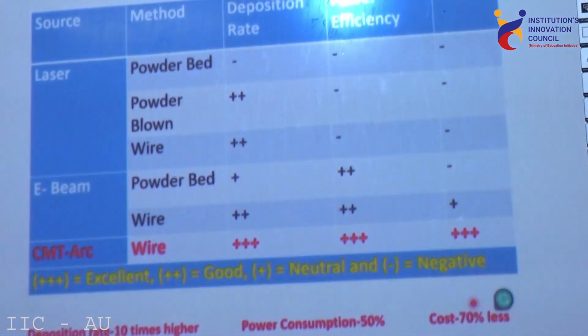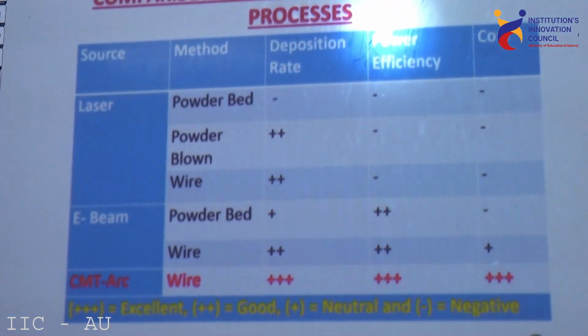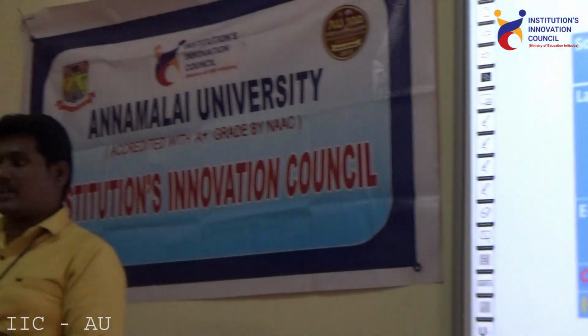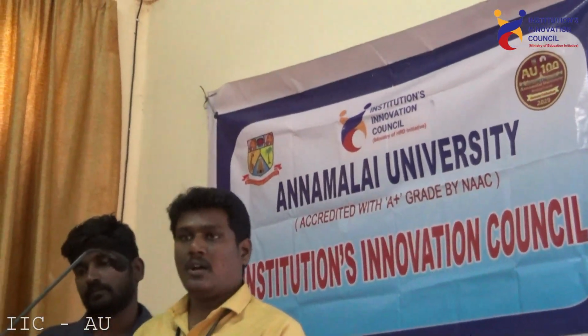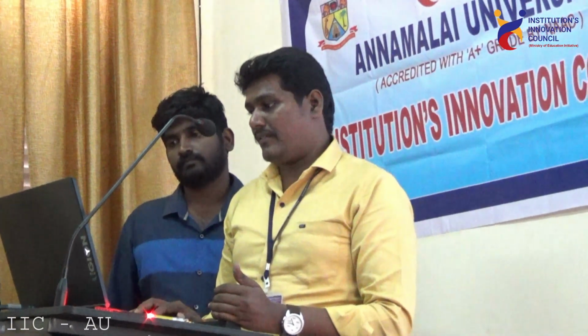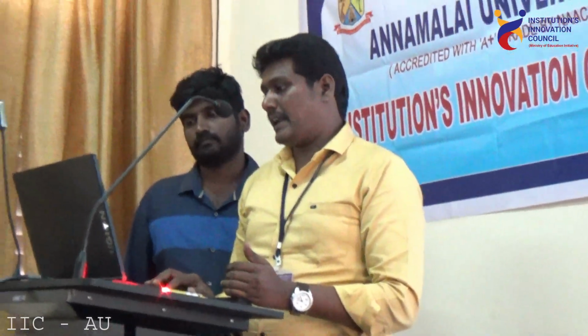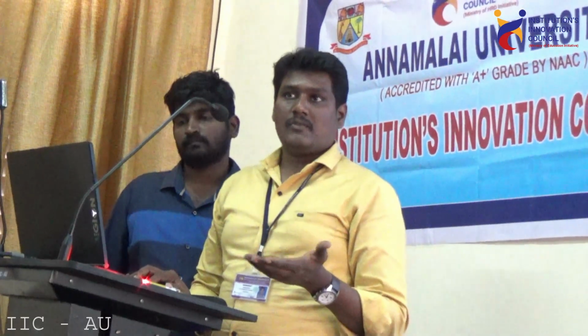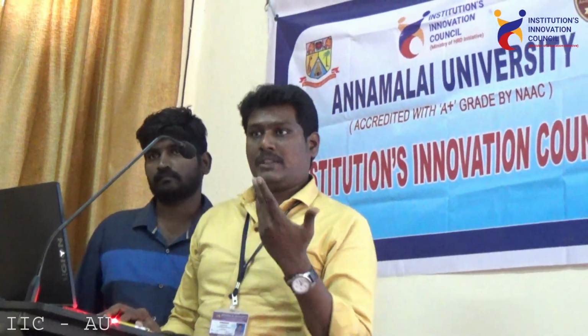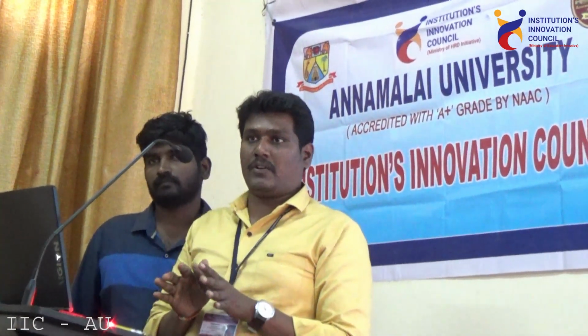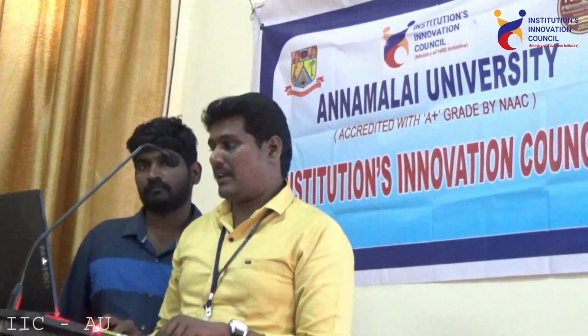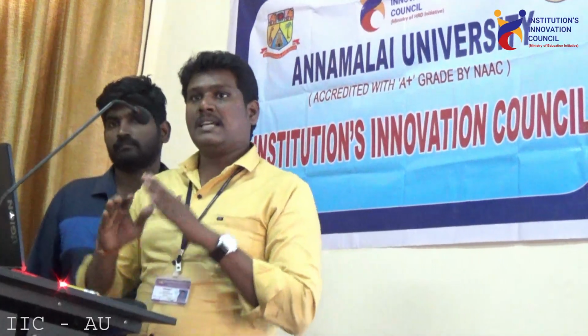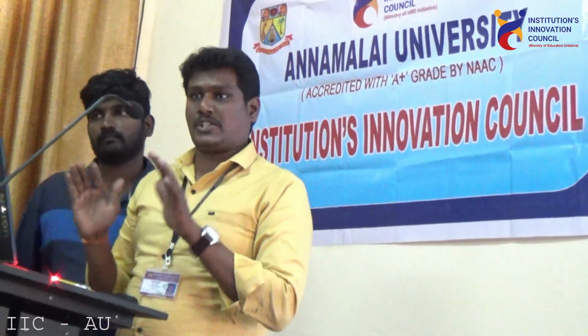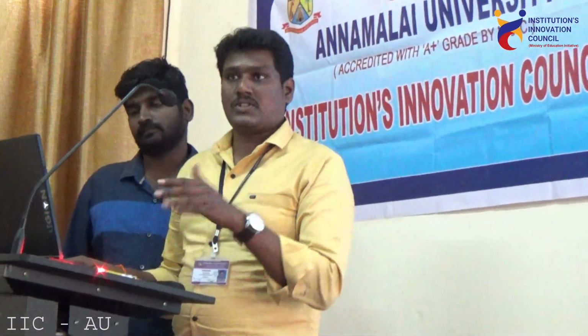And when comparing between the processes of additive manufacturing, that is between the methodologies, these two are powder-based additive manufacturing, laser and electron beam, and this is CMT. This is the comparison that we have given. In all the cases, say deposition rate, power efficiency and cost, the CMT component has a 10 times higher rate of deposition, which means 10 kg of component can be produced within an hour. In power efficiency, it takes a lesser amount of power to produce the component compared to the other additive manufacturing processes, and cost-wise a 70% decrement can be achieved in CMT process based components.